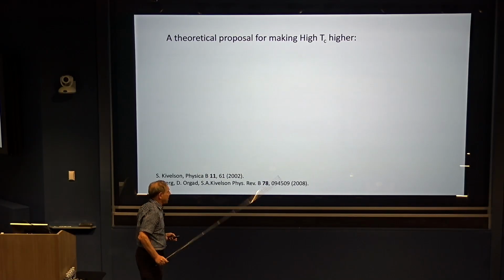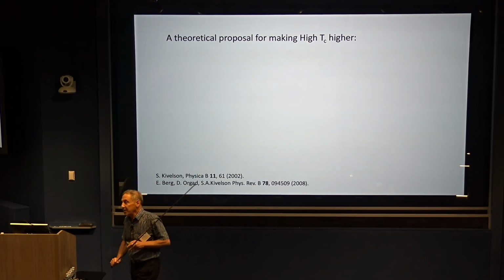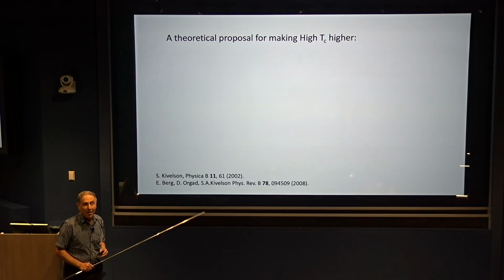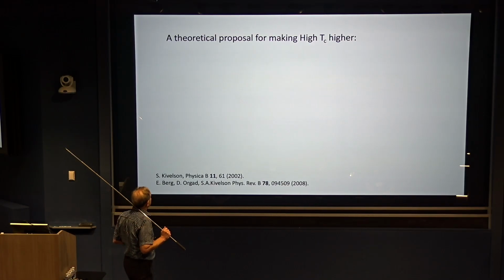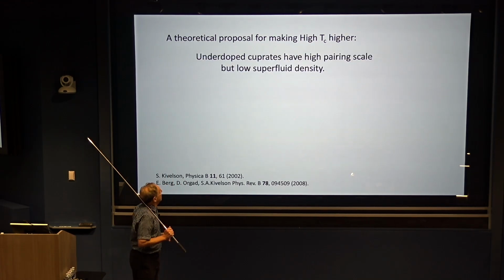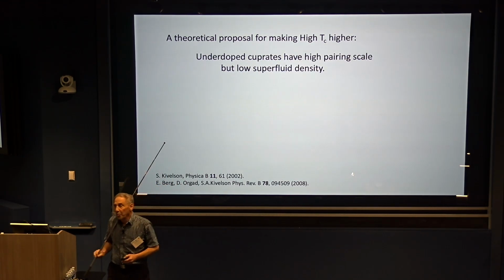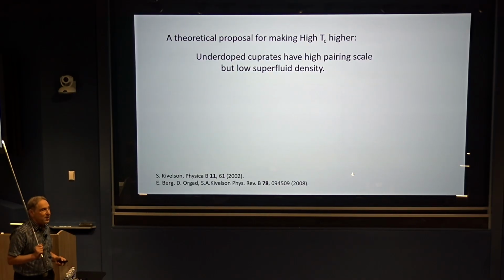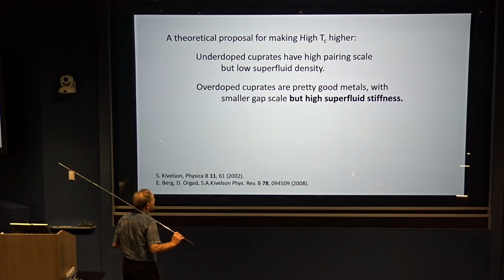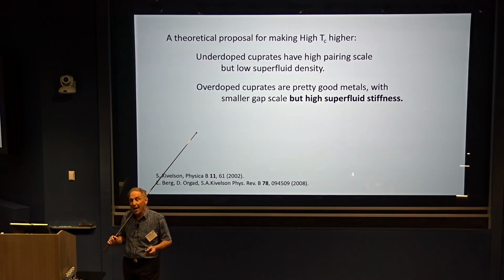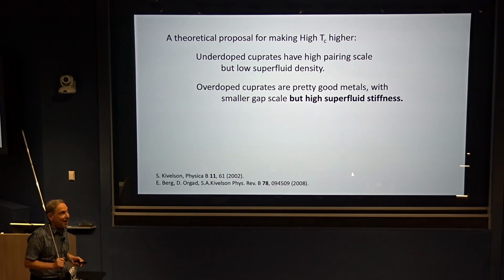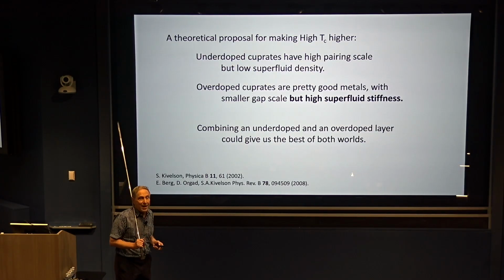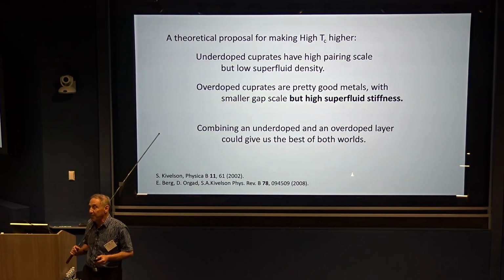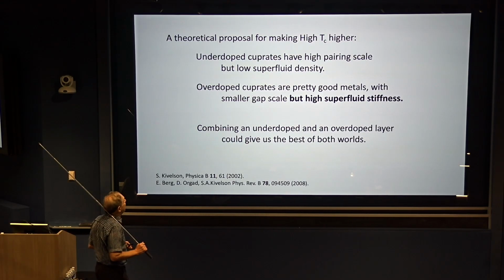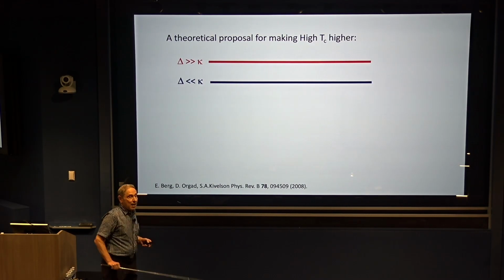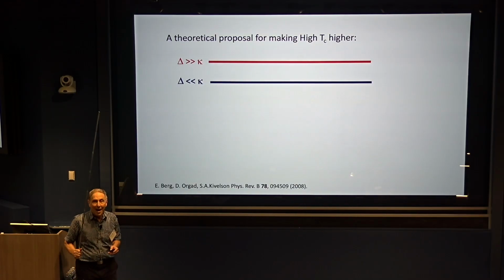Okay, so this then brings me to, again, not a new, but a newly interesting proposal for how to make TC higher. So the underdoped cuprates are not a higher temperature superconductor because they have low superfluid density. The overdoped cuprates have a high superfluid density, but a low pairing scale. Could we imagine combining these and inherit the best of both worlds? So that's the idea. And with Erez and Dror, we carried out some